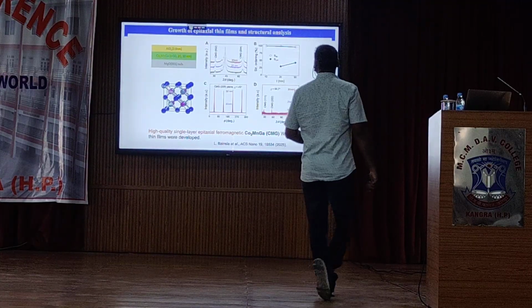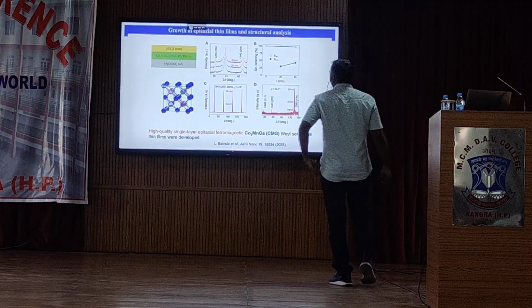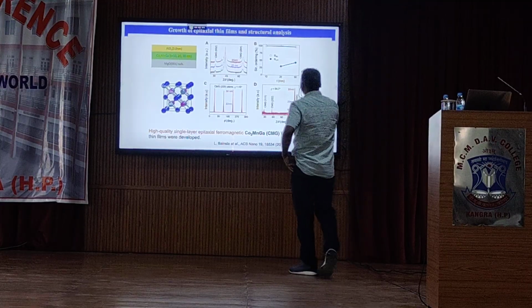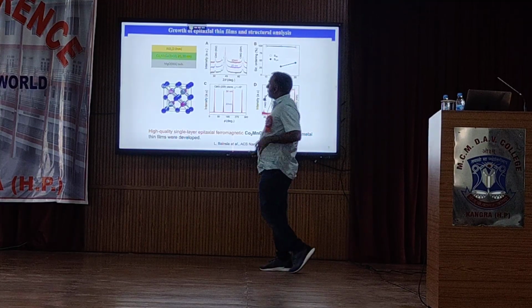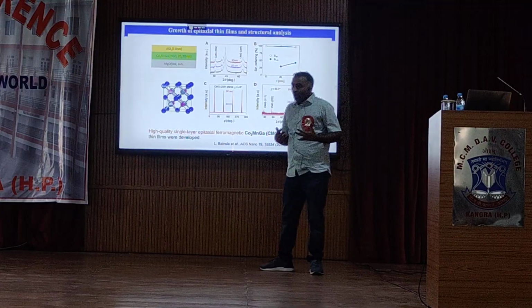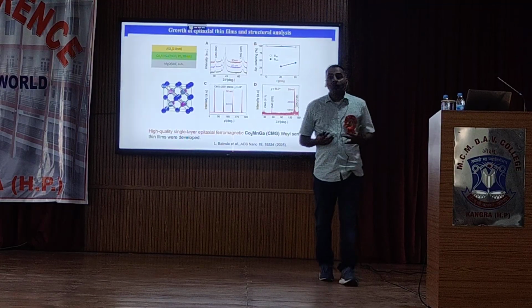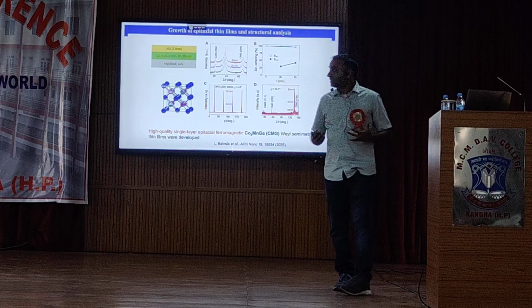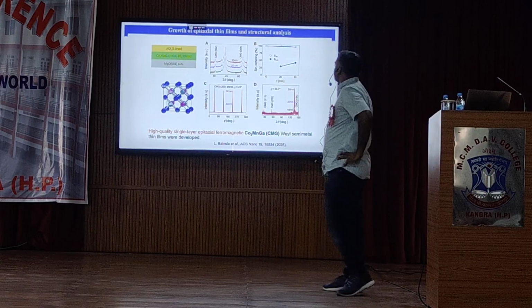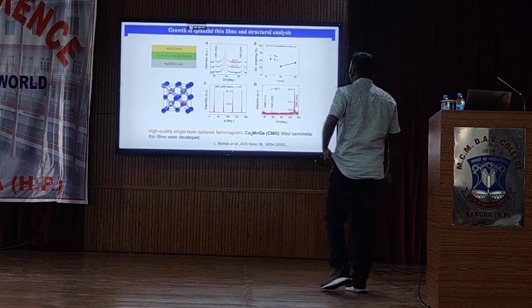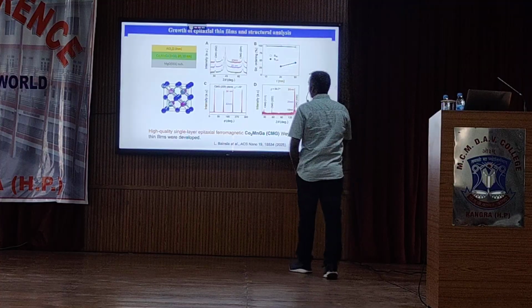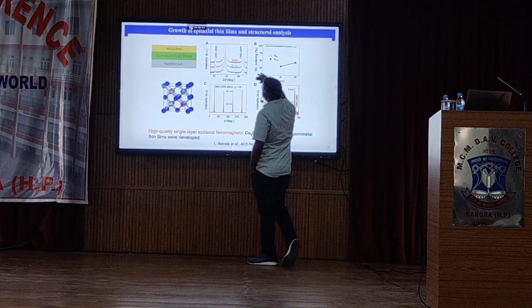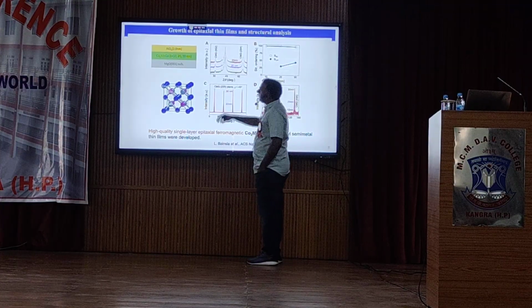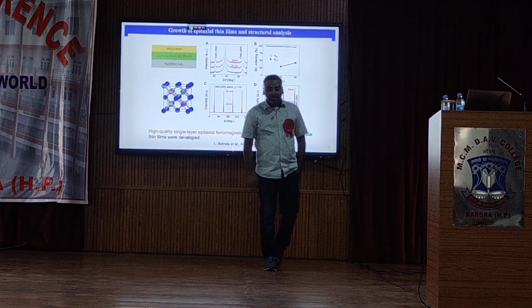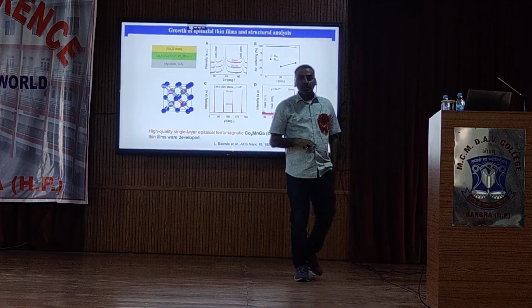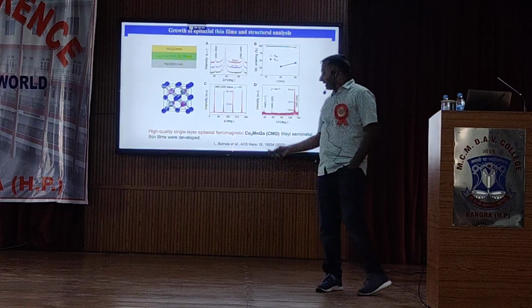So we first try to grow this material in thick film form, like 10, 20 nanometers. I am calling it thick because for us any thickness more than 10 nanometers is thick. So we first grow thicknesses more than 10 nanometers, and here I show the crystal structure of this material. We perform X-ray diffraction measurement, and we confirm our thin films are nicely single crystalline, similar to the bulk materials. As you can see here,